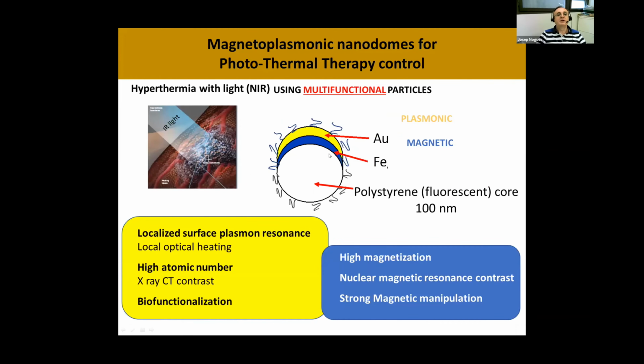What we call a nanodome is we have a polystyrene sphere, usually of 100 nanometers, where we grow semi-shells on top. And we grow two types of shells. First, an iron shell, which is magnetic, and then on top of that, a gold shell, which is plasmonic. And with this structure, we want to do optical hyperthermia for cancer treatment.